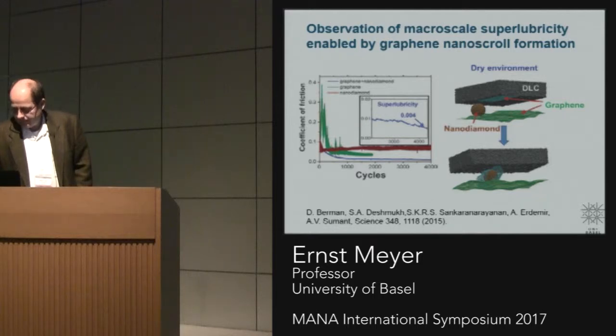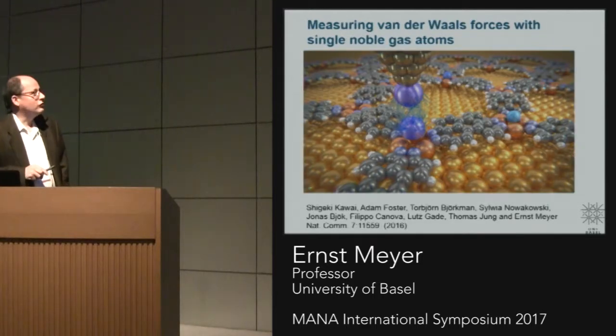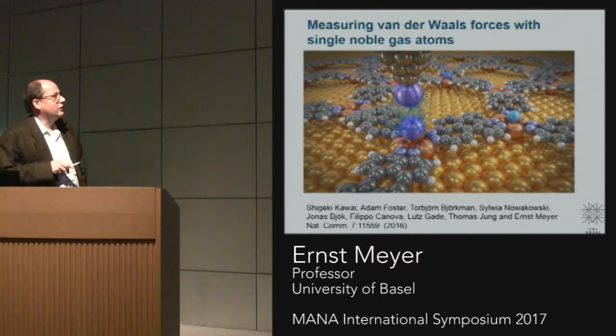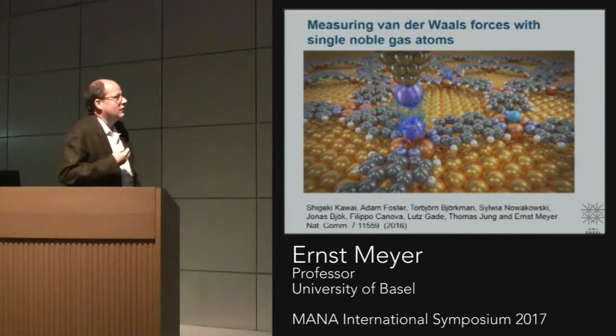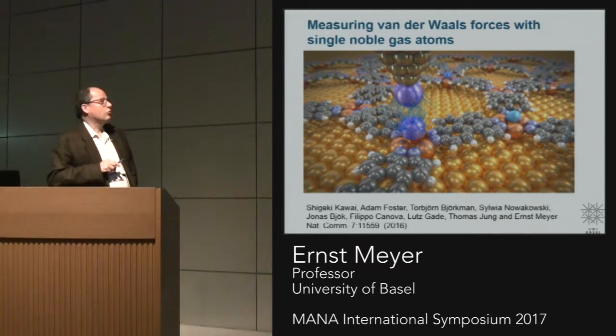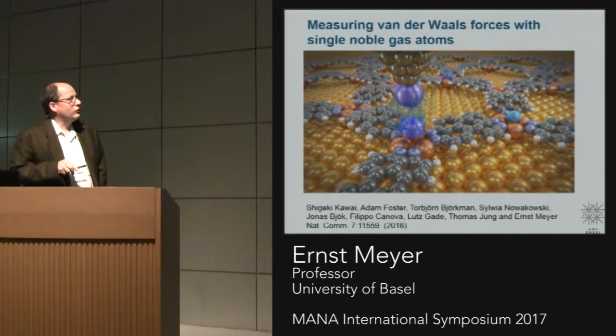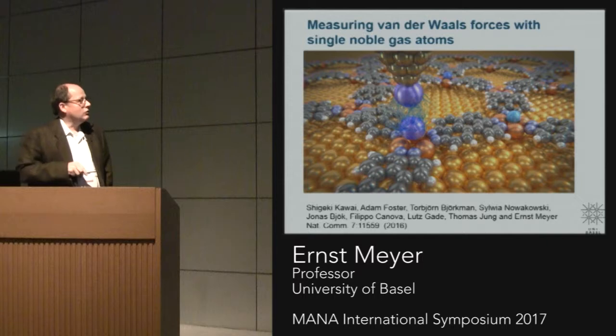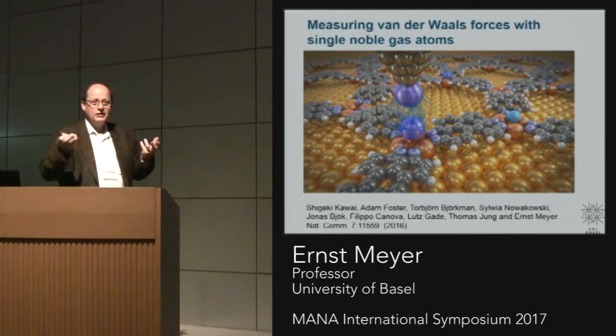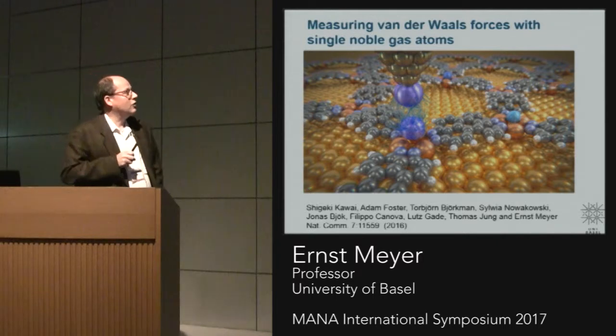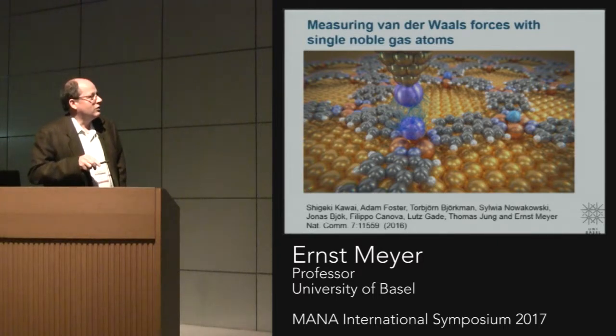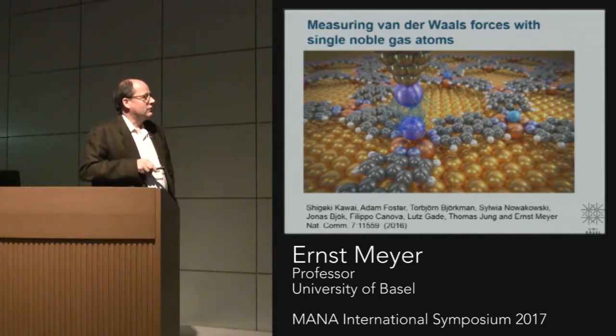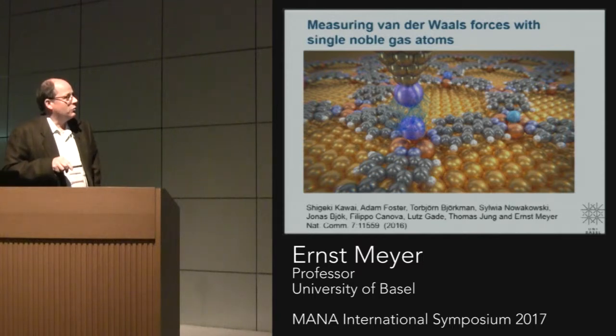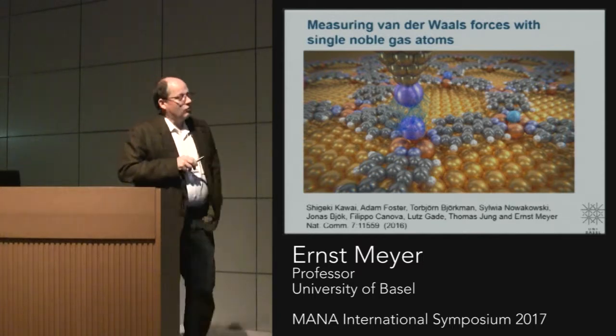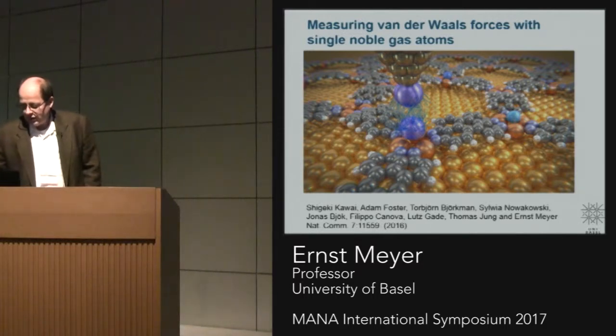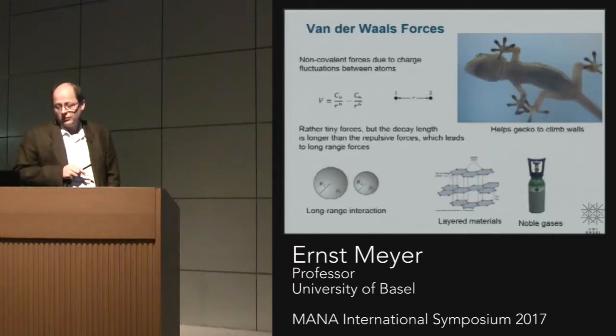Okay, so I think I have not so much time left, but I quickly wanted to show you something completely else, but also quite an interesting topic, and it really shows a bit the strength of nowadays force microscopes. So this is van der Waals force between single atoms. So this is a xenon atom here and a xenon atom on the tip. So again, you use the tip as a probe. So you pick up an atom and you deposit the whole thing on a molecular network here. As we will see, it's a metallo-organic framework with these copper atoms here, and that stabilizes the xenon, and then you can measure basically the interaction between single xenon atoms, the van der Waals interaction.